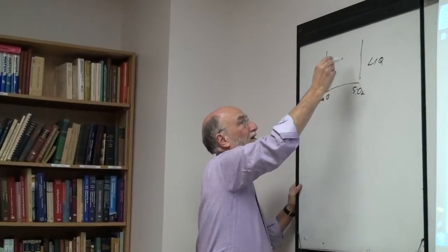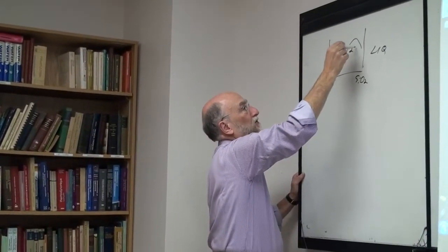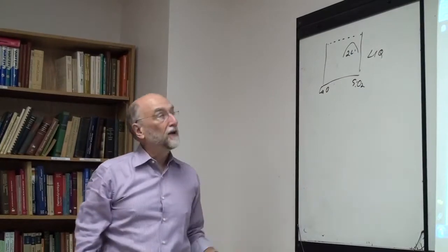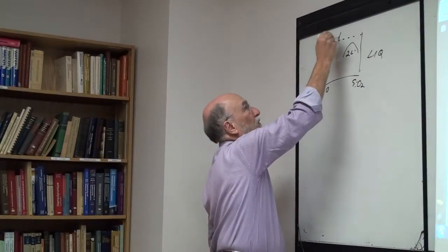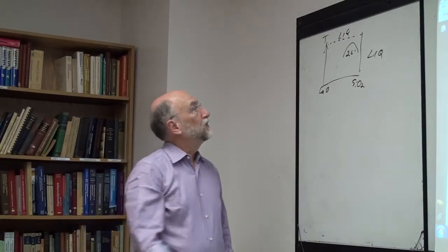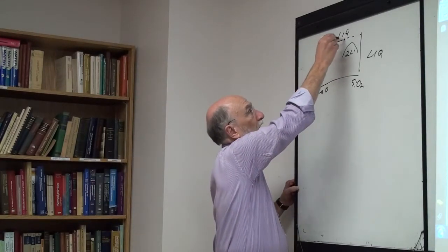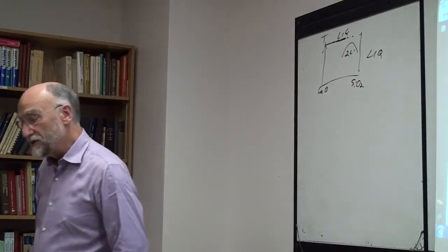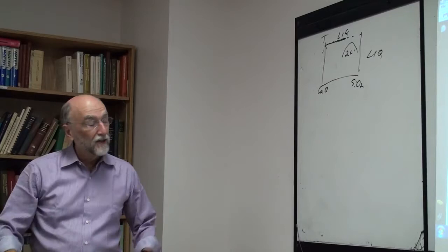Let's take, for example, a liquid phase, and we'd have here CaO, I'm talking about a liquid. In the phase diagram, there's a two liquid region here. If you're up here, at a high temperature, the liquid is completely miscible in all compositions. But there are many systems in which the whole region around here is quite ionic. Calcium oxide is ionic, and the silica goes into the ionic liquid.